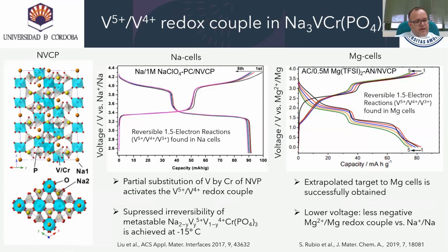Extensive investigations have been conducted involving the partial substitution of vanadium by other transition metals such as chromium, leading to the Na3V1Cr1(PO4)3 geometry, in which the activation of the vanadium 5, vanadium 4 redox couple is possible. This material will be referred to as NVCP.